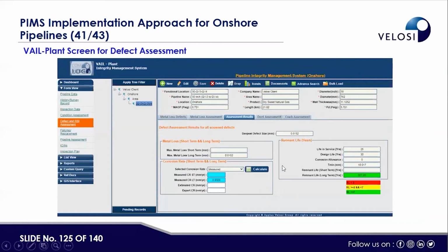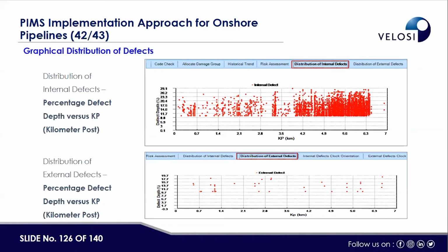Then from the defect assessment results point of view, if we look at the metal loss, then corrosion rate, then remnant life, we can see with the pipeline the life is coming quite high, but we should normally show whether more than 7 years or less than 7 years. But graphical distribution of the defects, the various defect data is there. Distribution of internal defect, percentage defects with depth versus KP, kilometer post, you can see this. And this is a normal defect depth in percentage point of view. The maximum defect size was 29.1%.